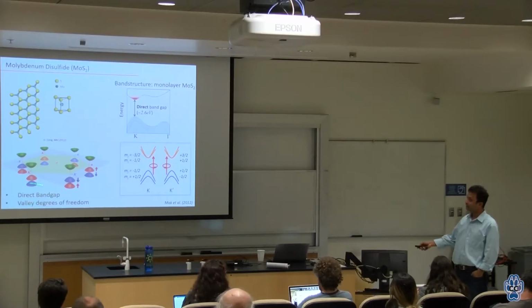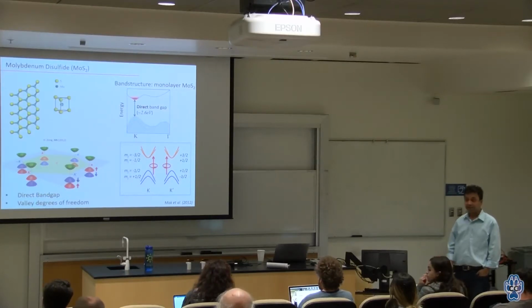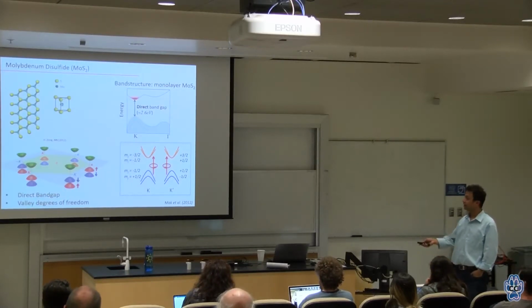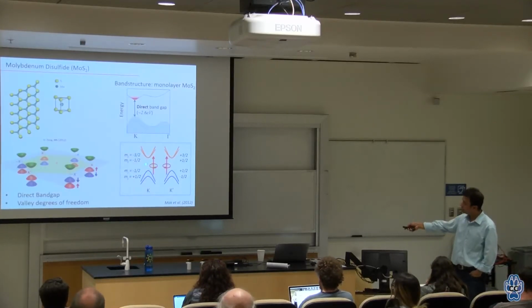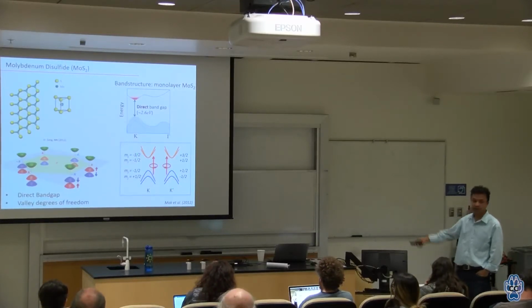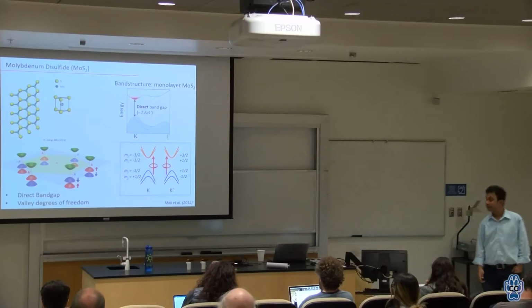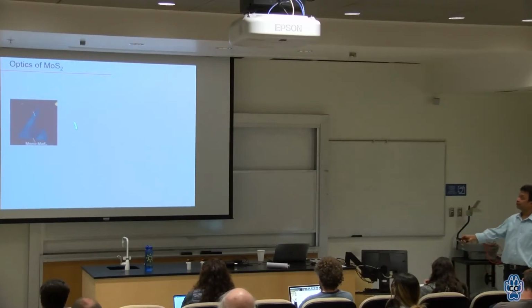Again, it's a direct band gap at the monolayer level, and then you have valley degrees of freedom. You can see here that when you have this kind of circular motion, you are talking only to the K point. When it's going the other direction, you are talking only to the K prime. So this is your optics.